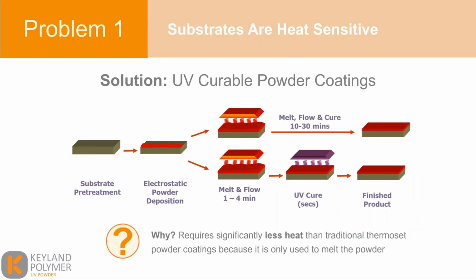So our solution to problem 1, substrates being heat sensitive, is UV curable powder coatings. Powder coatings have been around since the 1960s. They've been used primarily for metal applications. The image that you see in front of you, the top part is simulating a thermoset powder coating system. That is the traditional form of powder coating, where the material is applied in a powder form electrostatically onto the substrate, and then it is put into an oven where that coating will melt, flow, and cure over a period of 10 to 30 minutes and reaching temperatures up to 250 degrees C.